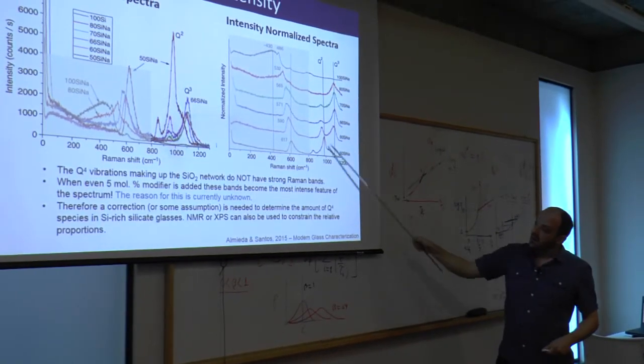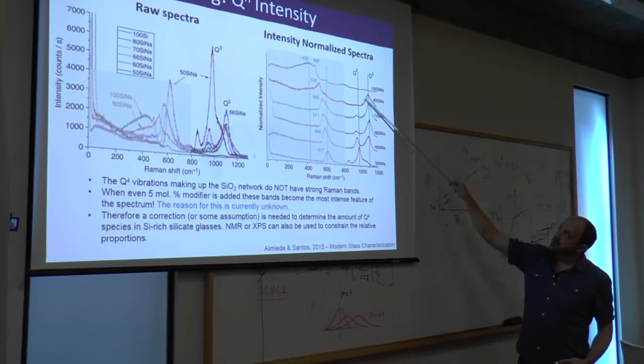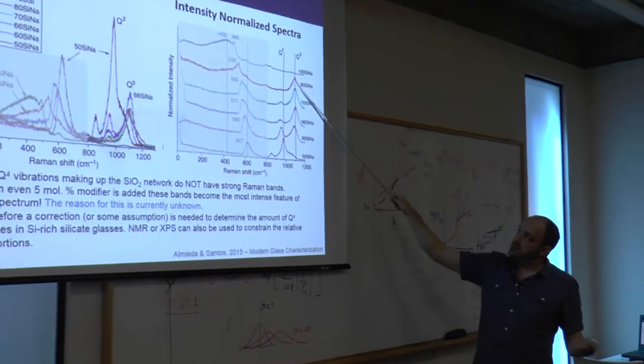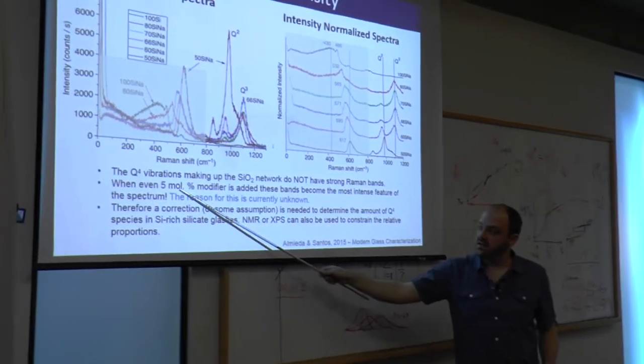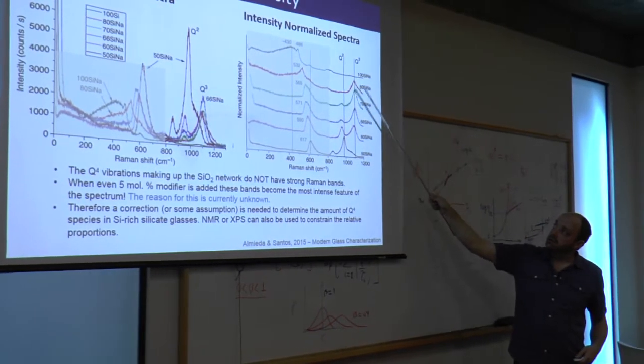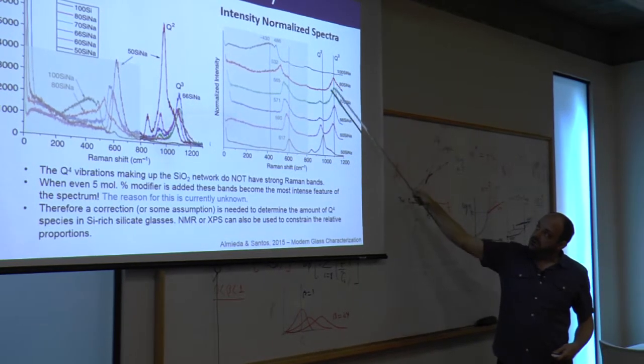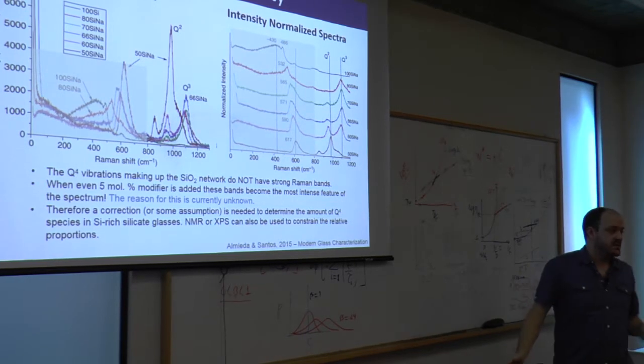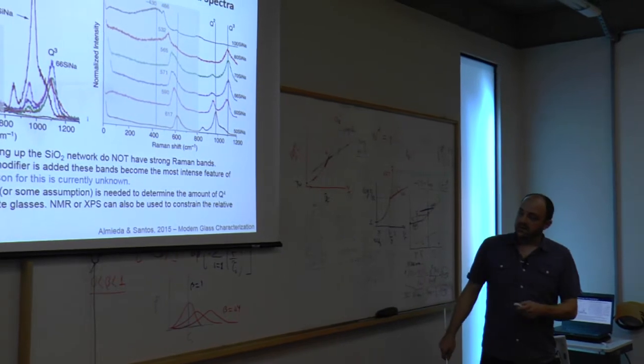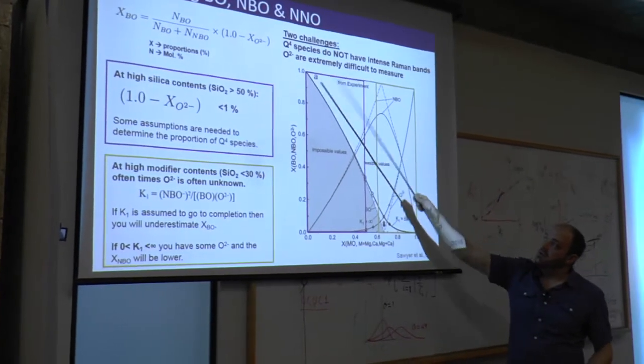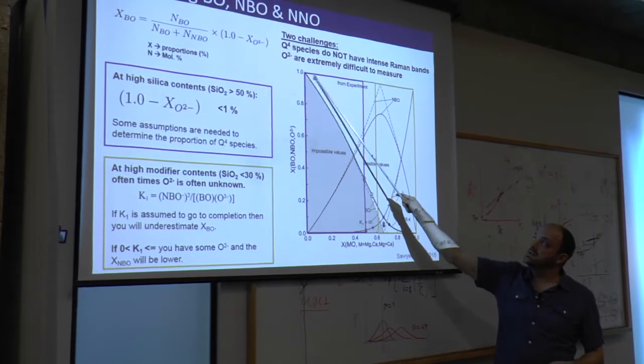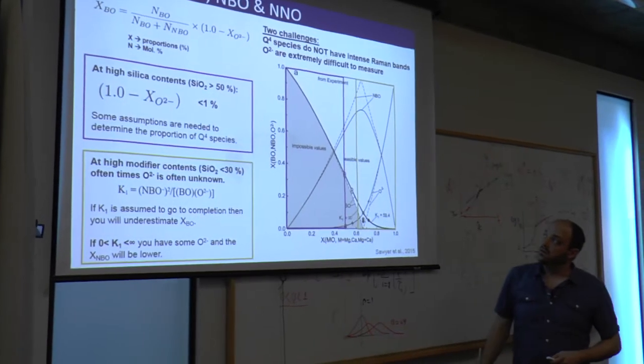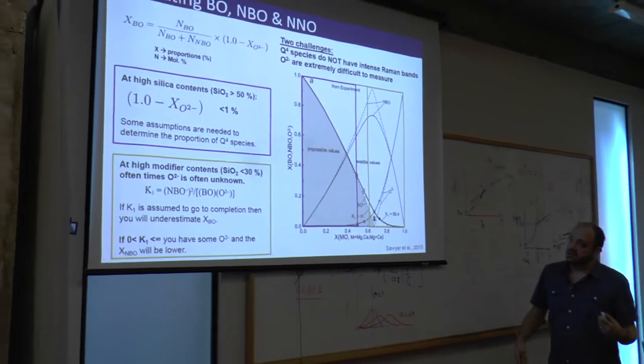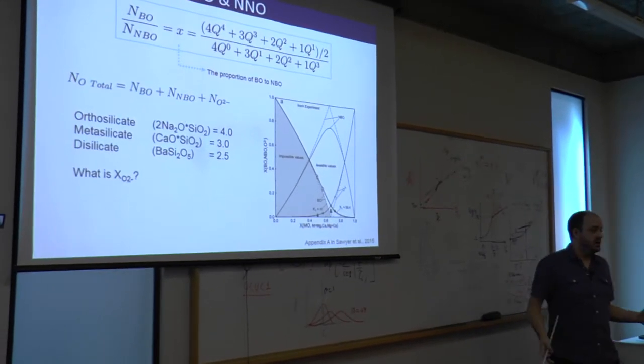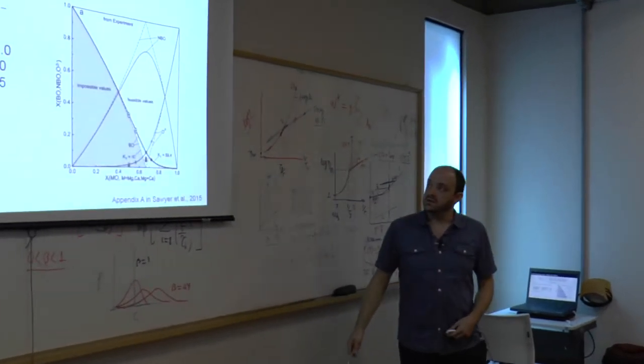So we see here nice behavior for pure silica. The reason why we get such a strong band as soon as you add sodium or any modifier in this region is not really known. But after 5%, the intensities seem to be proportional, and we can make a nice model going from, as you increase the modifier content, Q3s to Q2s to Q1s and so on. So you need to make some assumptions about those Q4 species. I'm not going to go into that because everybody does it a little bit differently for silicate glasses, but you should be aware that it's really difficult to actually determine the proportion of Q4 species. So if you think you have Q4 species and Q3 species here, you might only get one band from the Q3 species. So you need some other way to test your assumption about how many Qn species you have and how much bridging and non-bridging oxygen you have in the system.